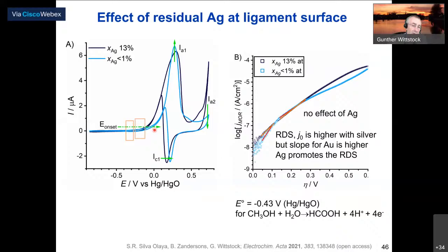And that's then the result for the methanol oxidation. So here for different concentration of remaining silver. So the initial material is this one, 13% surface atoms is silver. And after cycling in sulfuric acid, it's less than 1%. So with the silver, we see an earlier onset of the oxidation of methanol. So that's the oxidation of methanol. However, a lower current at the top. And then here, a few other situations here, also an earlier onset of probably carbonate formation, and then also a shift in the potential for the surface gold oxide reduction. If the surface is depleted from silver, then we see higher currents here, however, a later onset here.